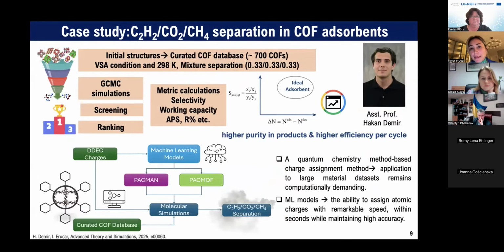So this is the first case study. In this work, we aim to identify the best performing COF structure for acetylene separation. So this is a kind of high throughput screening work. Here we need initial structures, and initial structures are taken from the curated COF database. Around 700 COF structures are available. And we consider vacuum swing adsorption conditions, which means 1 bar adsorption pressure, 0.1 bar desorption pressure at room temperature. And we model mixture gases here. So you can see we have acetylene, CO2, and methane gas molecules. Here we perform the GCMC simulations, and then we do a screening. After the screening, we rank our materials to identify the best candidate.